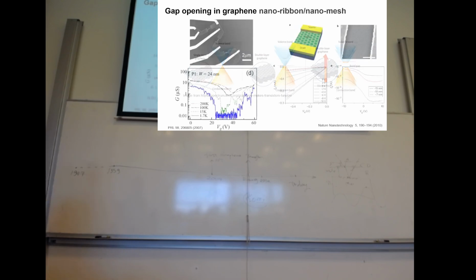Also, people have done some other experiments. Very good examples are the two here. For example, Philip Kim's group managed to etch graphene into very thin nanoribbons, and then there is a localization gap over there down to 1.7 Kelvin. But it's not a real hard band gap of a semiconductor. It's just due to localization effects.